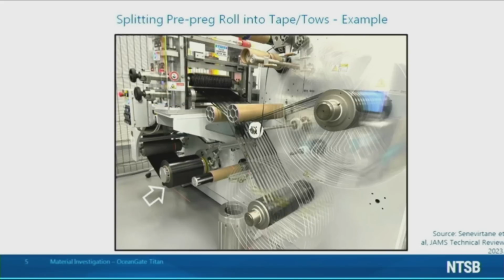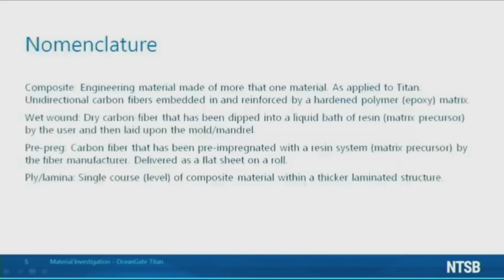A rolled up sheet of pre-preg is loaded into the machine and is sent through a series of cutters, producing a large number of tapes or tows. The tows are then rewound onto individual spools. One of these individual tows could contain thousands or even tens of thousands of individual carbon fibers, depending on its width and thickness. The pre-preg tapes that we saw in the previous slide are clearly very thin, so objects built up using layers and layers of these tapes will have a laminated structure. One course or level of unidirectional material is a ply or lamina.